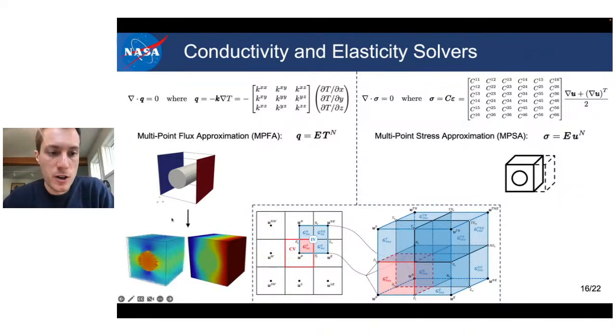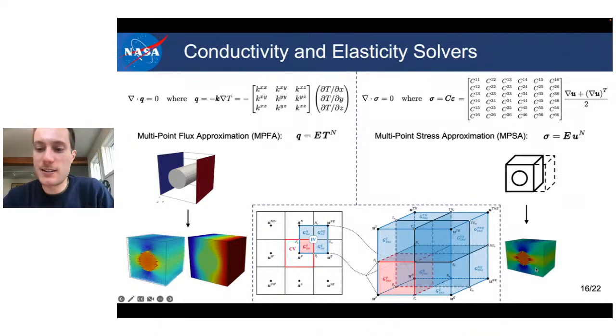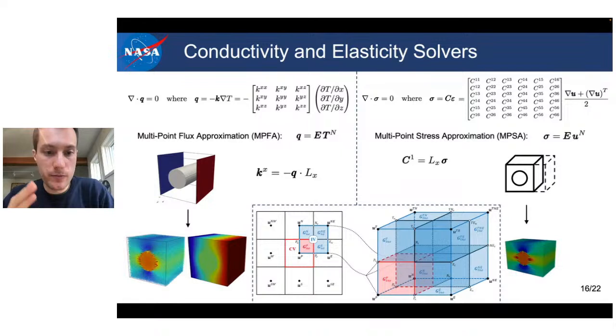Except that for the elasticity, we also have to include the shear cases in order to get back the 6x6 tensor. So once you solve and converge the local temperatures throughout your domain, what you get out of the conductivity function is a temperature field as well as a flux field. For the elasticity, it is instead a displacement field as well as a stress field. We use these converged fluxes and displacements to compute back and average out the effective property, the conductivity on the left and the elasticity on the right. And this gives us back just a column of our tensor.